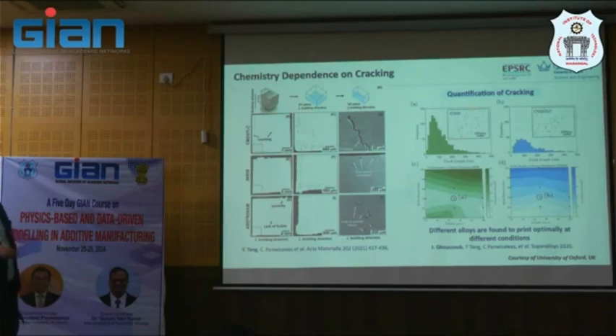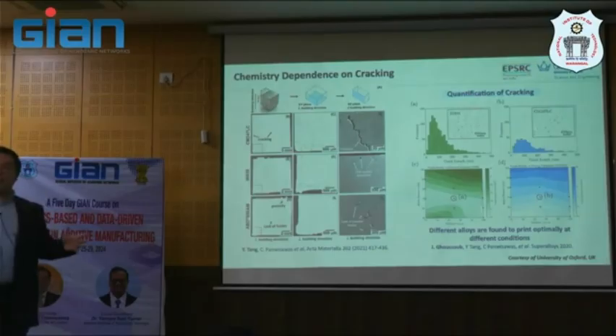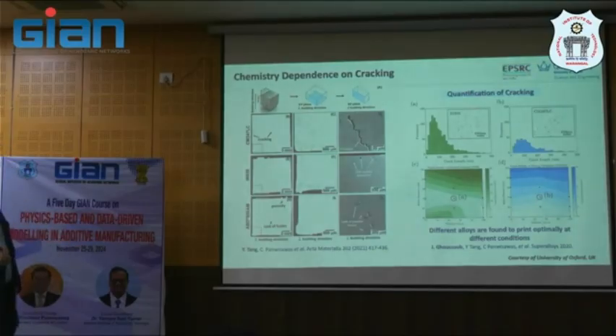And you'll see this is 2 millimeter. It's quite a large area. Actually, this is basically the whole sample. So you can get an overview, the map of the crack. And what we do next is compare with the newly designed alloy here. There's no crack or very minimal crack. We will show you some statistics later.